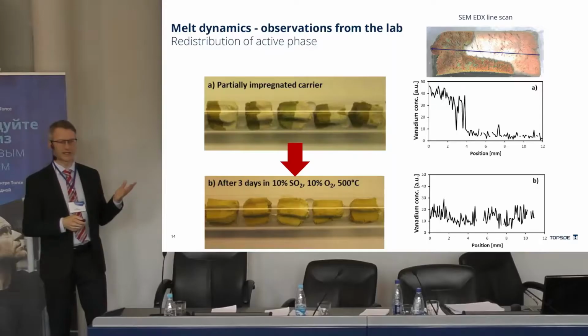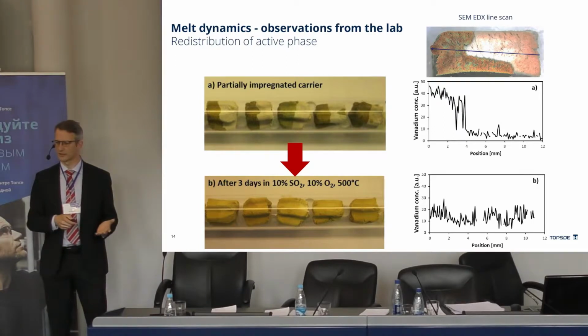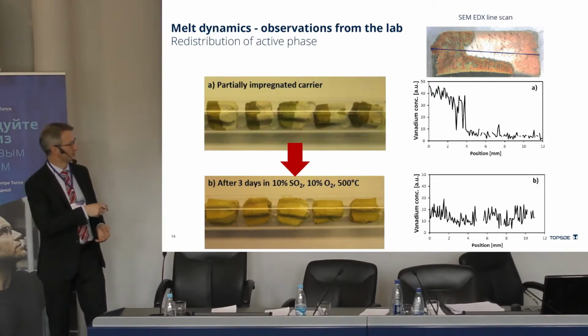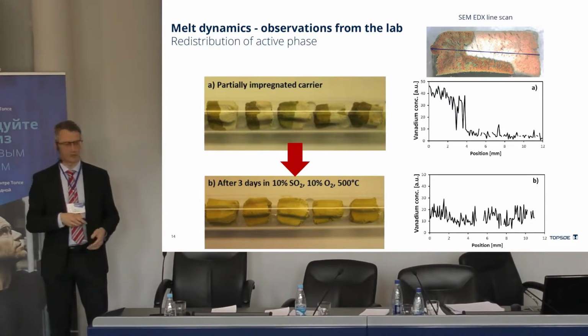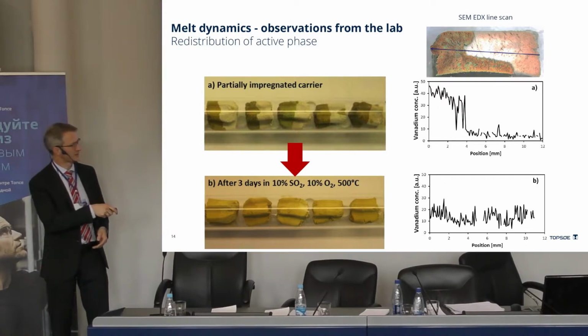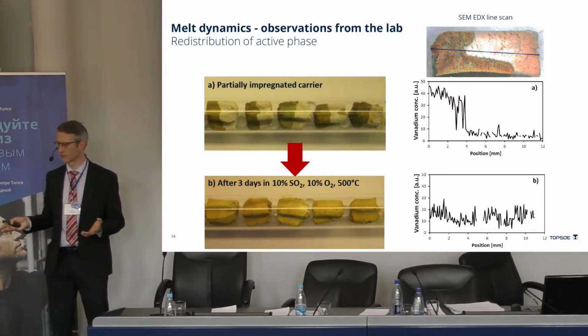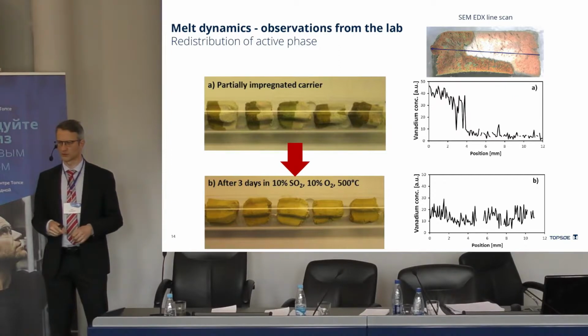So what happens if we put it on stream in the lab for 3 days? Then it looks like this. You can see that the vanadium has its yellow throughout the pellet, and you can see from this analysis that now vanadium is distributed all over the pellet. So this shows in a simple way that the melt is quite mobile and will distribute on the carrier depending on the operating conditions. But of course we want to see it on the nano scale. We want to see what takes place in the catalyst when it's operating.